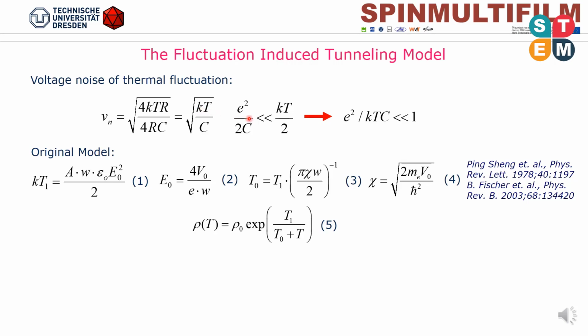For fluctuations to occur, the electrostatic energy per electron should be much larger than the thermal one. In our example, the ratio of both is in the order of 0.1. The fluctuation-induced tunneling model describes conducting grains separated by energy barriers subjected to large thermal fluctuations. The tunneling occurs between large metallic grains across insulating barriers with a width W and an area A.